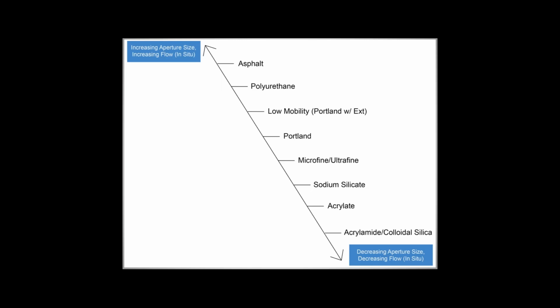Now, if we were to look at the different aperture sizes and increasing flow for in situ, where we might use these types of grouts, this is just a quick chart. The upper limit of the chart talks about aperture size. Larger aperture size, you're going to get the Portland cements, the low mobility grouts, the polyurethanes, and the asphalt. But as sizes start to get finer and finer as we move down to the right side of the scale, you're going to drop into the ultrafines, the sodium silicates. And as you get into matrix porosities, you may put in an acrylate or the acrylamides, so the colloidal silicates.